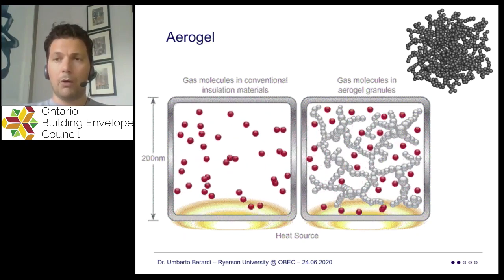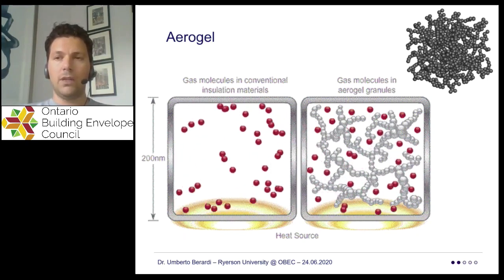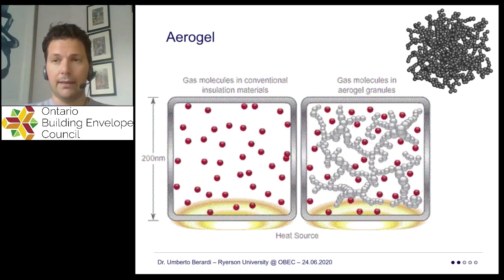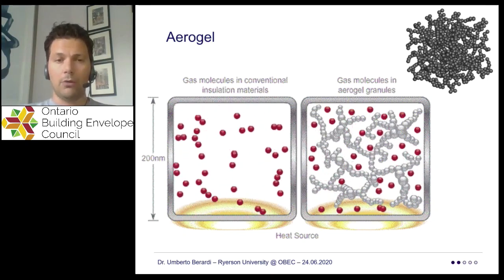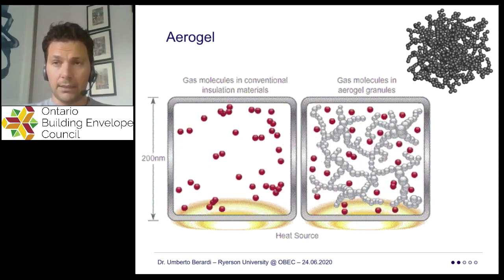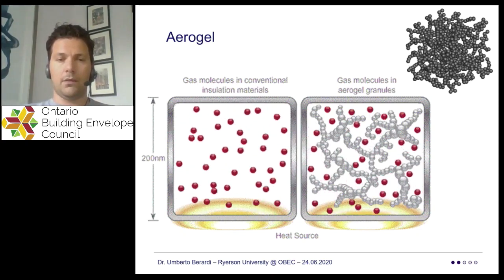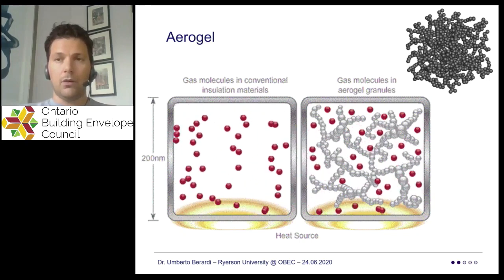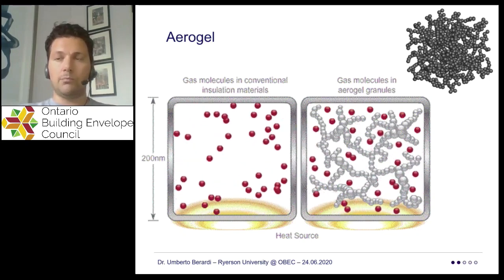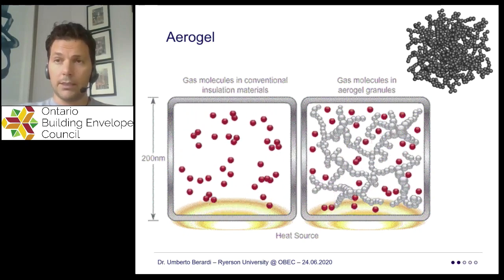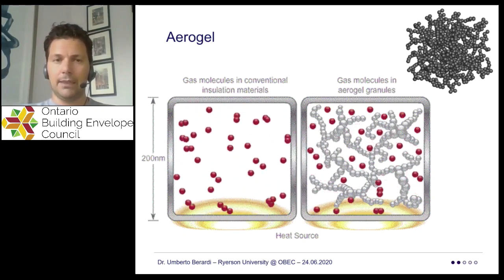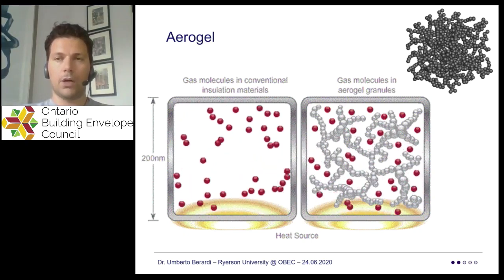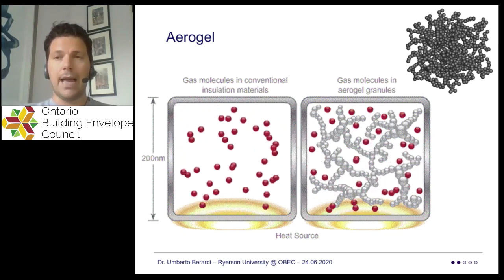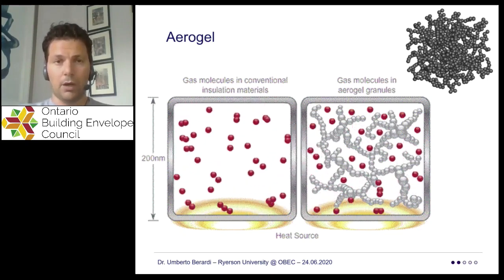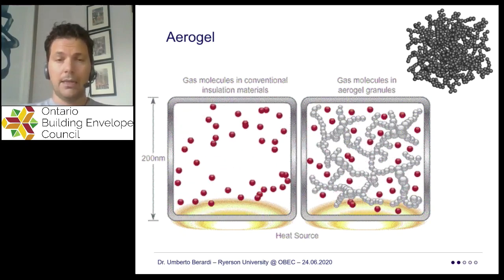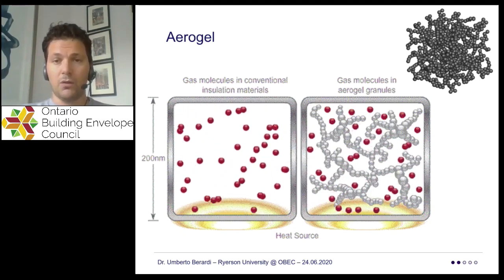And even if you are speaking about a closed cell foam, you still have a blowing agent that is there as a gas. And this gas is moving around, and by moving around, it can move heat from one side of this square to the other side. So although we typically consider an insulating product a material that is fully solid and only has a thermal conductivity acting through conduction, in reality, in the cavities and voids of these products, there is convection happening. And if the void is big, convection is more significant.